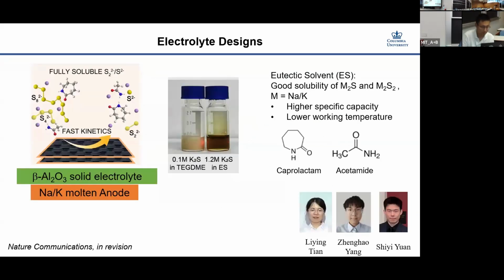So as you see, the main reason for the low capacity in sodium sulfur batteries is that you form solid phases. So we try to find electrolytes that dissolve sodium disulfide and sodium sulfide. In this way, we hope the kinetics in the liquid phase will be better. So we tried different electrolytes, and we found that sulfur actually has high affinity to amino groups.